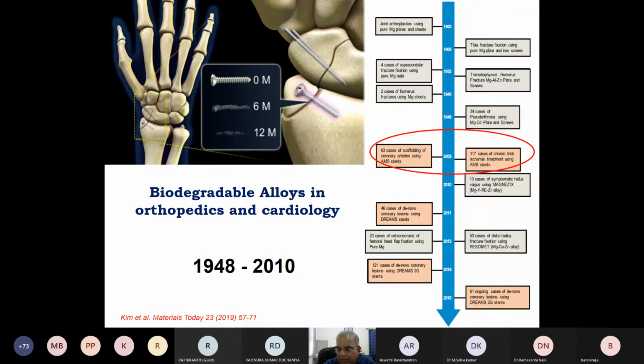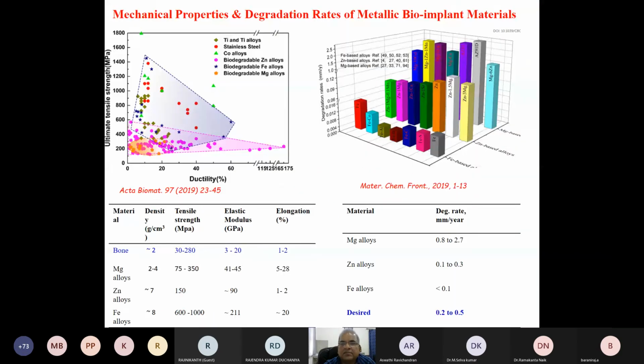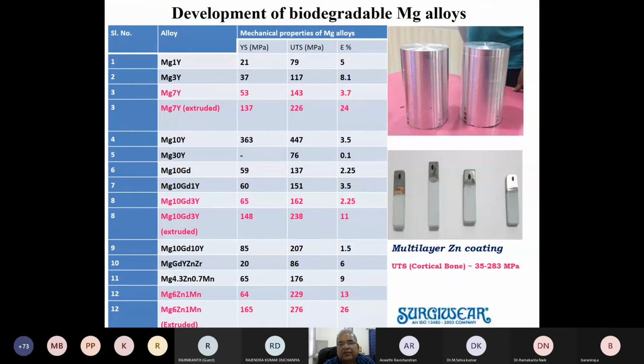So we started dealing with this problem with the help of SERB again. I am not going into the properties or the corrosion rate of the different implants, but we have developed different magnesium alloys at a subsequent large scale, casting of 10 kg. And this magnesium was also produced by NML technology. NML developed a technology of magnesium production in the 1960s and transferred it to an Andhra-based industry. There they produced magnesium. Now the industry has shut down, and the magnesium is lying with NML. So we use that magnesium and develop magnesium rare earth alloy, magnesium zinc manganese alloy, and so on.